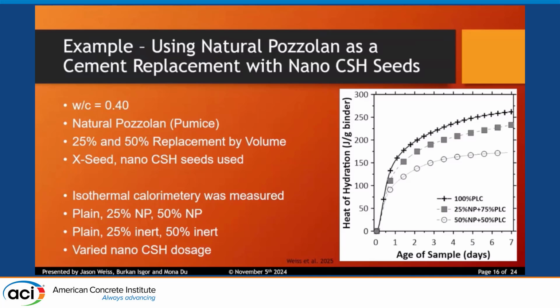I'm going to do everything based off of isothermal calorimetry, so we're going to try to match up the heat of hydrations. As I mentioned, we did the natural pozzolan, we did it with an inert quartz material, and then we're going to vary the nano CSH seeds. What we notice here is a reduction in heat, and you may say, what does that really mean? You have a reduction in reaction, a reduction in strength development in those two systems.